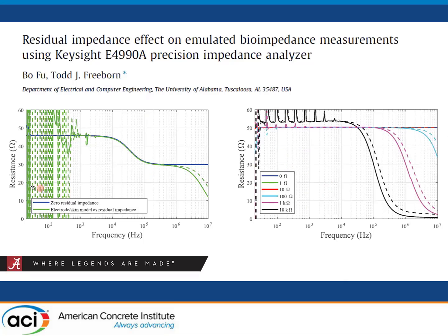And so what is shown here is measurements taken, these are Bode plots, using an impedance analyzer on a system that has some type of residual impedance. And we start with the 0 ohm residual impedance, increase that. And we see when we get to relatively high residual impedance values, we start seeing a bunch of just what you might consider noise, spurious measurements in our system, because theoretically we should, in this example from this paper, always measure 50 ohms. But when we start trying to measure our 50 ohm resistor, we're getting all this up here because we have this residual impedance present in our system.